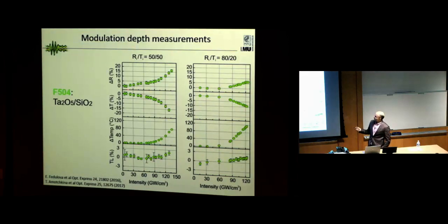Actually, what's written here: we observe that by increasing the intensity, our reflection starts to grow and the transmission falls down. It means our 50-50 ratio has changed to another one. What we observe as well is that the temperature of the sample at high intensity just grows. And this graph shows that our losses slightly increased, but almost not. What's the evidence for that? It's not two-photon absorption, but the Kerr effect. The same we observe for another ratio, when the reflectance is 80% and the transmission is 20%.